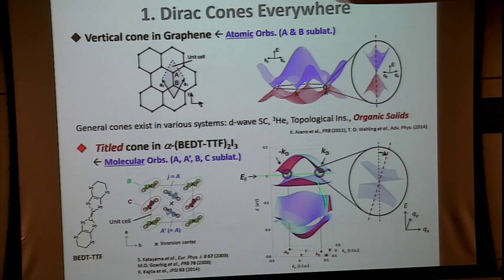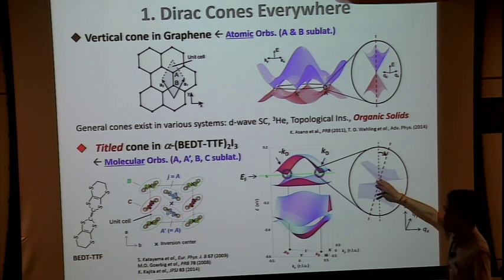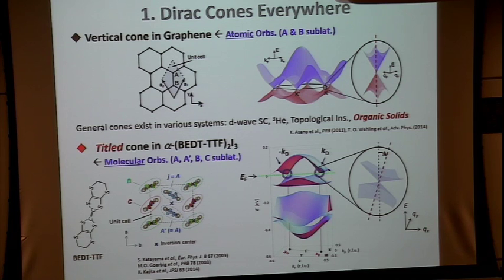However, in the organic material, this is the band structure calculation. The unit cell contains 4 molecules, so the band structure contains 4 bands. And the Fermi level is fixed here because this is a three-quarter filling. And this is the expansion of the profile of the dispersion around the Fermi level. So a tilted cone, a seriously tilted Dirac cone, is predicted. And the ratio of the Fermi velocities is one order different, precisely speaking, 8 times different. Okay, and the transport measurements confirm that massless Dirac fermions are there in these materials.